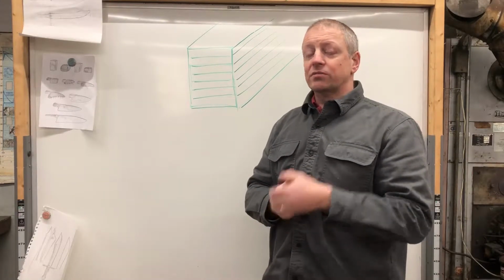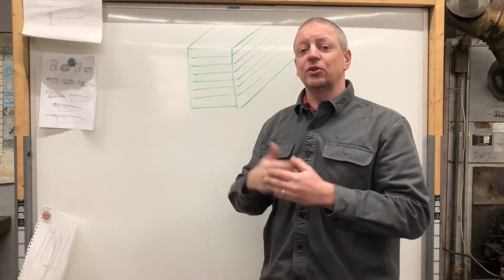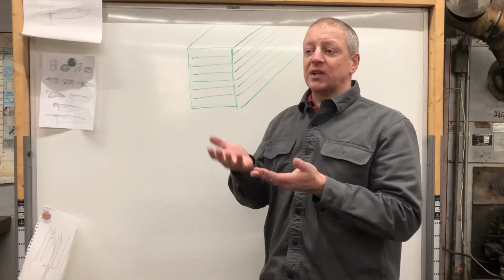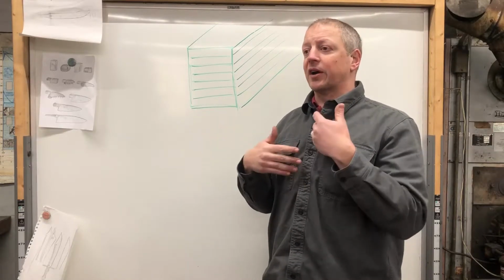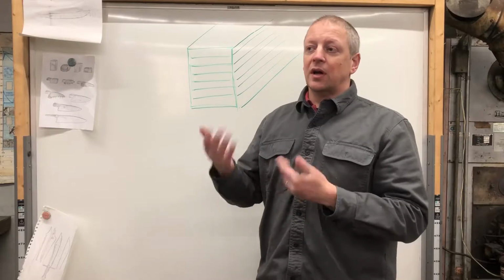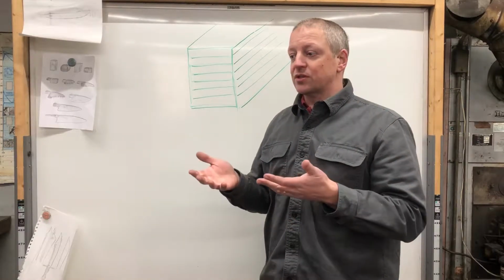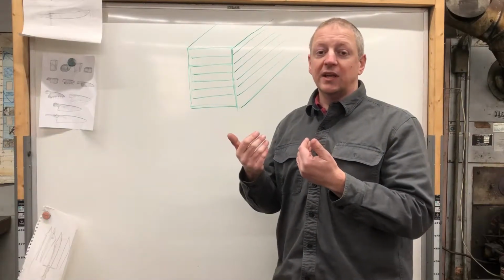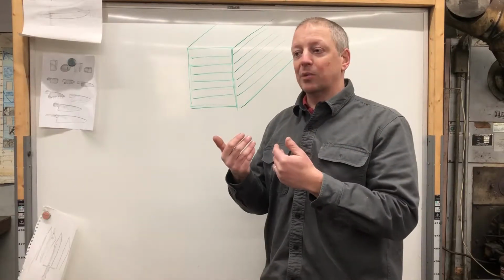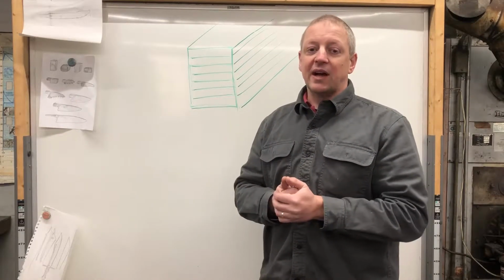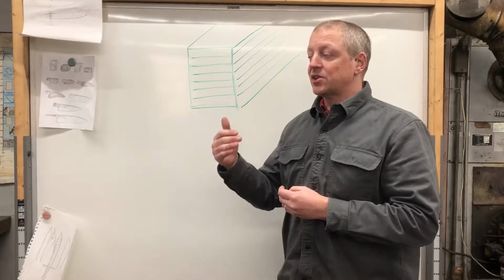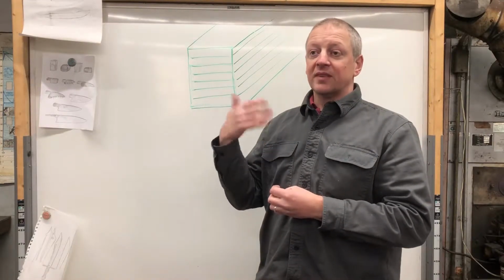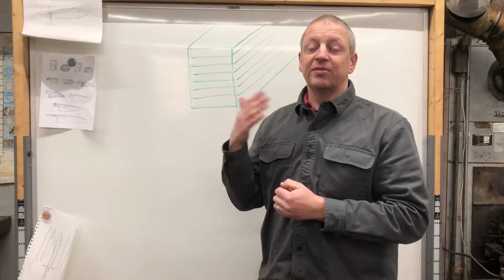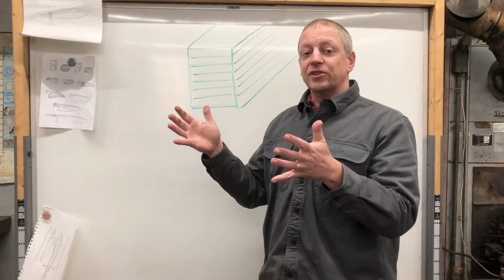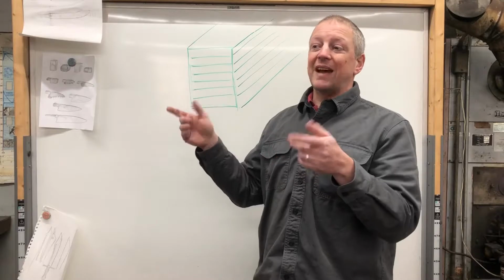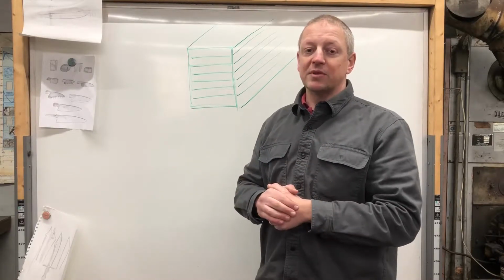Throw it in the forge. Forge should already be fairly hot. You can have the two come up together to some degree, but you don't want to be starting from a cold forge with a cold billet because it'll just take a long time to heat up, and that whole time while it's heating up, you're going to be getting oxidation. The temperature of the billet needs to be fairly elevated before carbon migration to the surface is faster than oxidation by atmosphere.